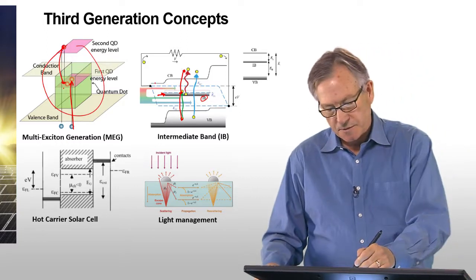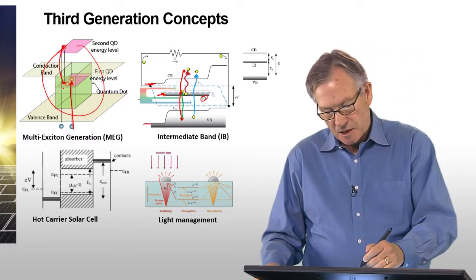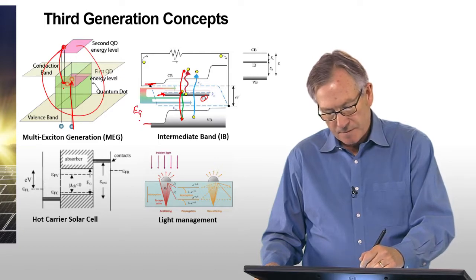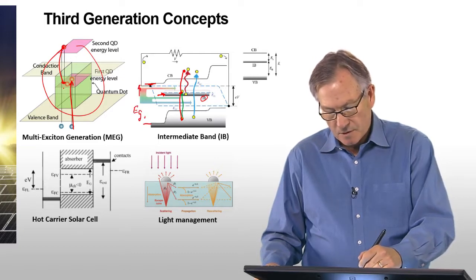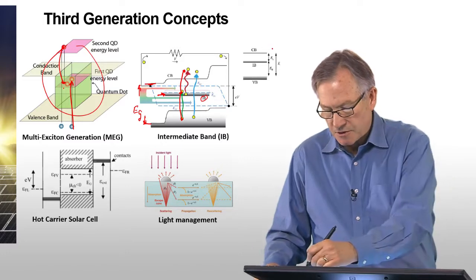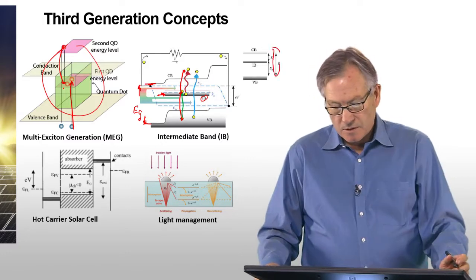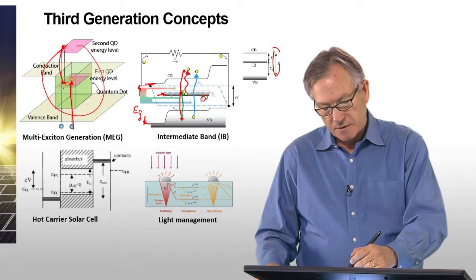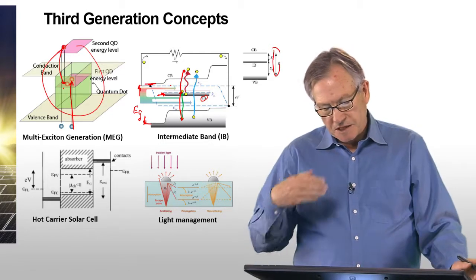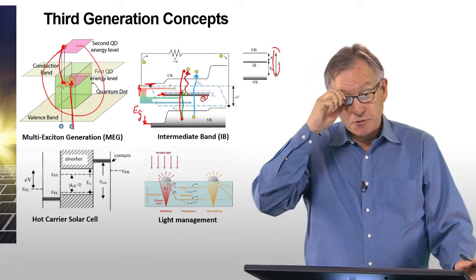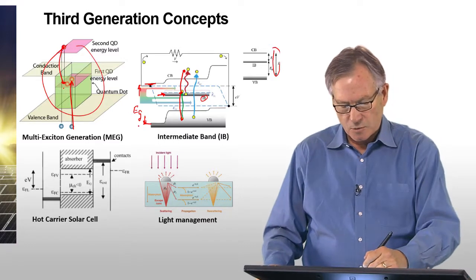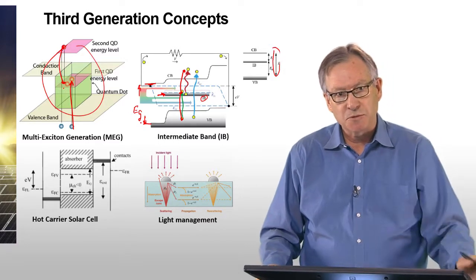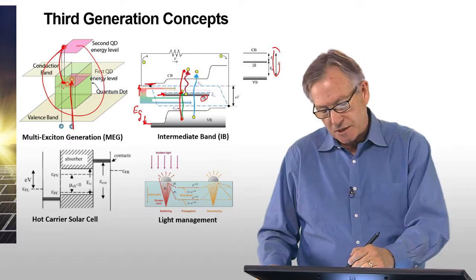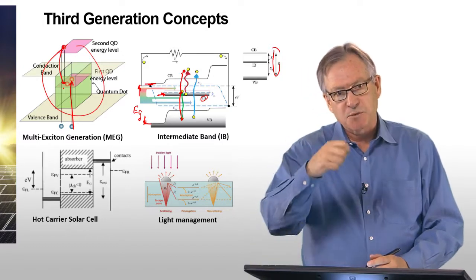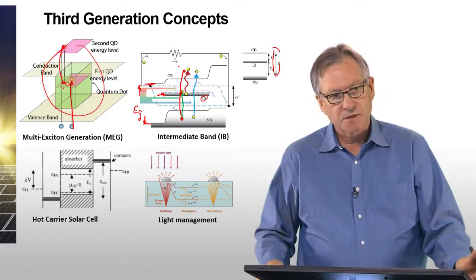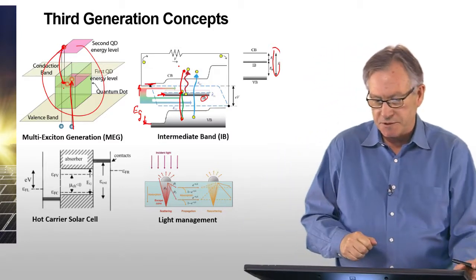So there's a host material which has a band gap EG, as shown over here. That's wider than these intermediate levels. And so basically the idea is that you can produce a voltage that corresponds to this wide band gap, E sub G, but you're harvesting electrons at a photon energy smaller than the band gap by this 2-step process. So it's kind of like a 2-photon absorption process.